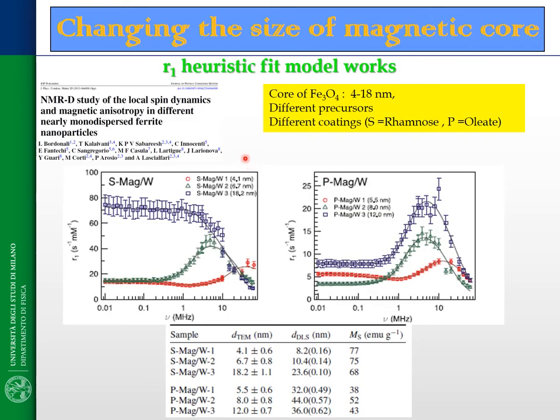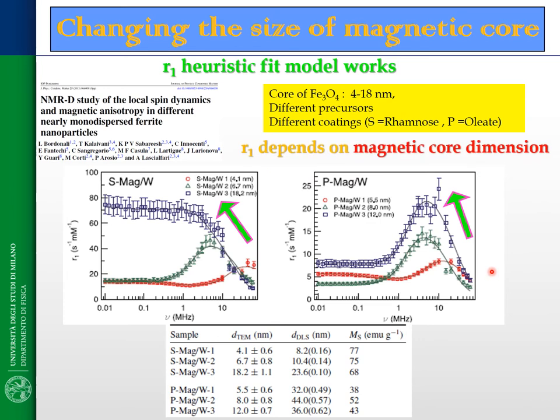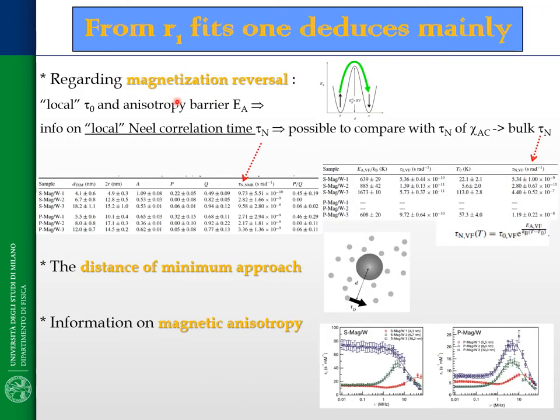Starting from these evidences, we studied many types of magnetic nanoparticles experimentally. We obtained the relaxivity profiles starting from R1 profiles. In this case, we studied R1 profiles of magnetite nanoparticles coated in different ways. We started to demonstrate that experimental data confirmed the prediction of the models — that the R1 relaxation properties depend on the magnetic core dimension. We also tested the model on our experimental data by fitting, and we obtained information regarding the magnetization reversal of our nanoparticles, the distance of minimum approach, and a quantitative idea of the magnetic anisotropy of our nanoparticles.